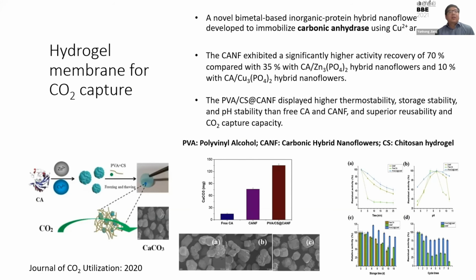So in this slide, I just briefly show a collaboration project. The result has been published in the Journal of CO2 Utilization, 2020. We have successfully synthesized a carbonic anhydrase hybrid chitosan hydrogel membrane for carbon dioxide capture. The amount of calcium carbonate produced by the developed membrane was 9 times that of free carbonic anhydrase. The developed membrane shows higher thermal stability, storage stability, and pH stability than free carbonic anhydrase.